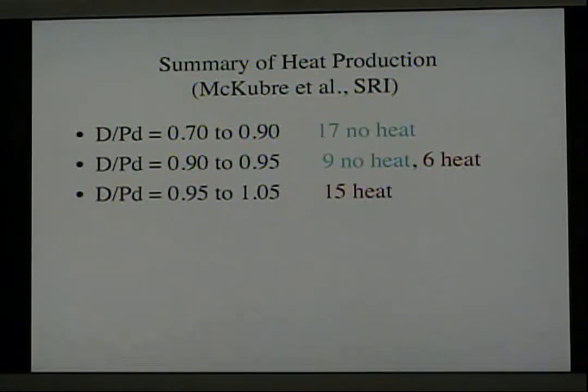Here's another example provided by McKubre. When material that could only get up to 0.9 was measured, 17 of the samples that were studied produced no heat. When material was found that could go from 0.9 to 0.95, 9 of the samples produced no heat, but 6 did produce heat. And finally, when the rare samples that can get to 0.95 and as high as 1.05 were studied, all 15 of these samples made heat.